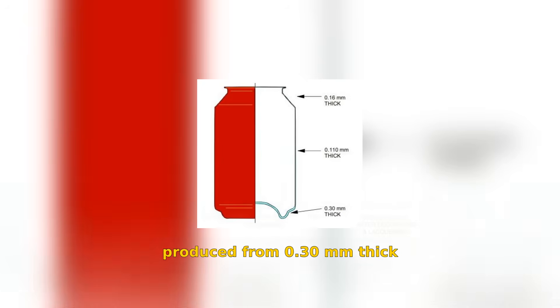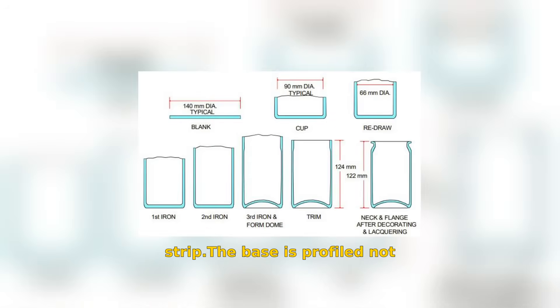Body is produced from 0.30mm thick strip. The base is profiled not only to withstand the high internal pressure, but also to ensure the base is stackable on the appropriate lid.